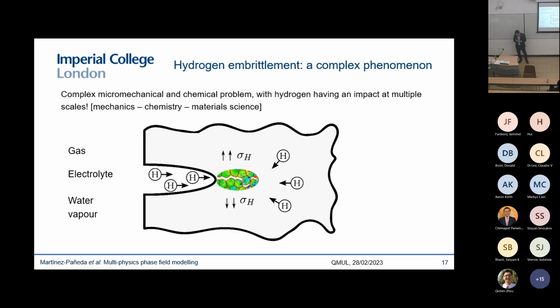And this is something that is, however, considered a long-standing challenge, and the reason is that hydrogen embrittlement is quite a complicated problem. First of all, it's quite multidisciplinary, but at the same time, it's also complex from the point of view of being multi-scale and from a physical point of view, difficult to understand. We do understand certain things, but there's many other things that we don't fully understand. So we understand that hydrogen atoms coming from gaseous, electrolyte, or water vapor environments will come into the material, they will diffuse through the crystal lattice, and they will accumulate in the fracture process zone where they will interact with the metal in many ways that, as I said before, we don't fully understand.